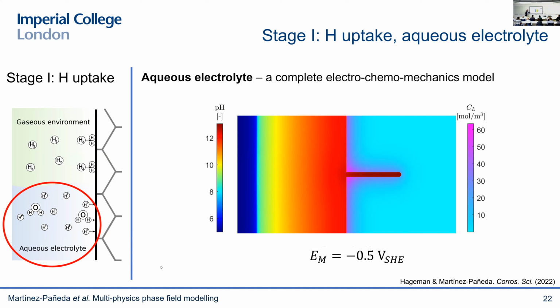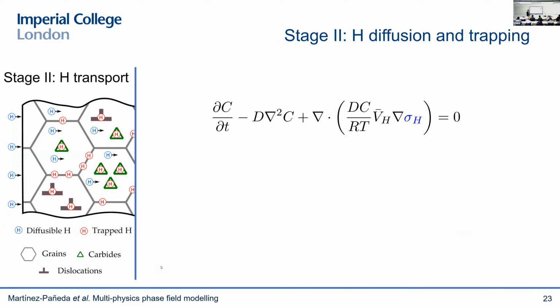And again, we can do this for different choices of material, for different choices of applied potential, for different choices of environment, for different defect geometries. We can use this virtual platform to predict the uptake of hydrogen under any condition and over any time scale that we're interested in. And then once you know how much hydrogen is coming to the metal, then you need to simulate the transport of hydrogen within the metal. So to be able to predict what is the distribution of hydrogen within your, say, industrial component.